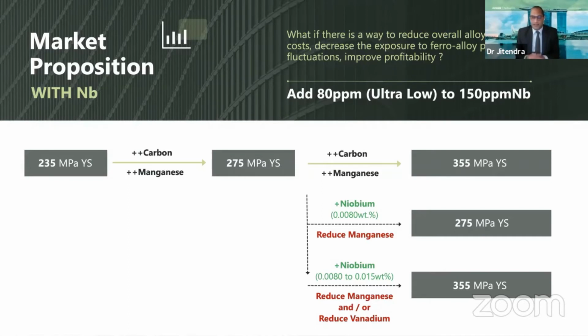And the proposition we're making here is that, from some research we've done and some industrial trials, which I'll go on to show the results of, we have found that these very, very low levels of niobium can be used in 275 to substitute manganese and save costs in the current climate. And also for some of the lighter sections of 355, the same thing can be done, either a partial or full replacement of manganese, or a full replacement of the vanadium addition that's been made to these steels.